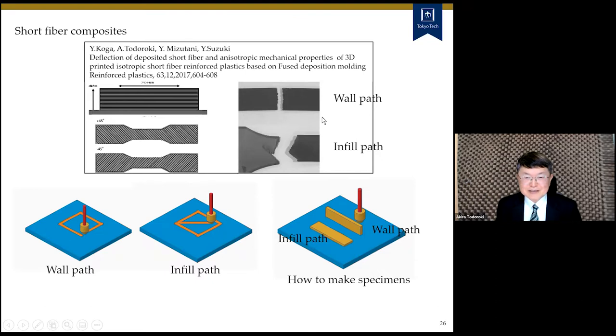Before that, I would like to explain what the wall path and the infill path are. To print, for example, this dumbbell type specimen, first the 3D printer prints the wall, I mean the outline of the specimen like this. So this is called the wall path. And after this wall path, the inside of the specimen is printed using an infill path. The infill path is usually plus minus 45 degrees to prevent thermal deformation.